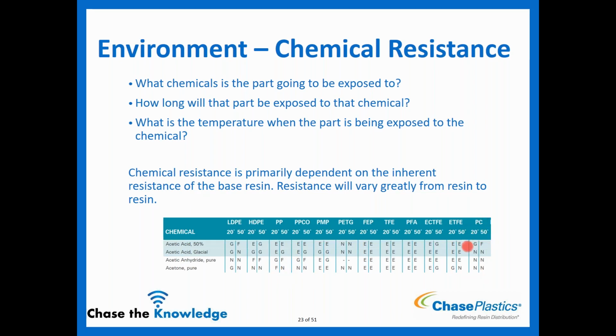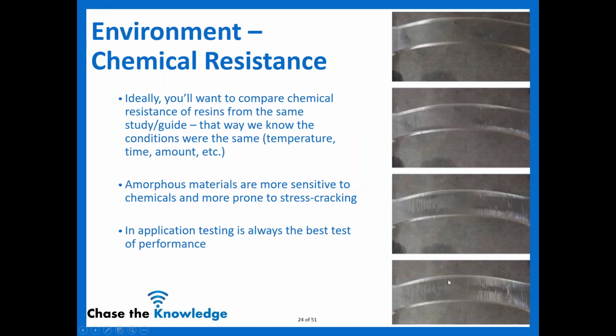And you'll see on average the polycarbonate, there's a bunch that attack it. It is an amorphous material. It's not as chemically resistant compared to your polyethylenes and polypropylenes that are your semi-crystalline materials. But again, very dependent on the base resin and the chemical being exposed to.